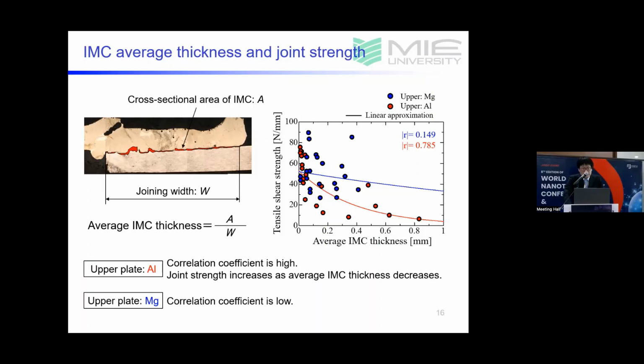When the upper plate was Al, as shown by red marks, the correlation coefficient is high, and joint strength increases as average IMC thickness decreases. On the other hand, when the upper plate was Mg, as shown by blue marks, the correlation coefficient is low. So we next focus on the joining area instead of the average IMC thickness.